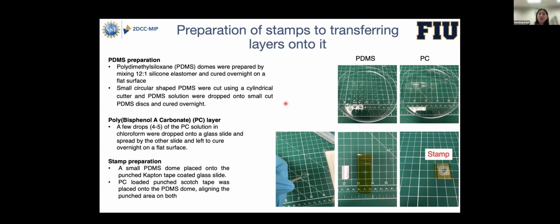And then how to make the stamp. For the stamp formation, we took a punched Kapton tape onto a glass slide, and took one small piece of PDMS dome and put it onto the punched area. We wanted to align the punched area with the PDMS dome. And then, using a scotch tape, we took a layer of PC material from the glass slide and put it onto the punched PDMS dome, and this is how the stamp was prepared.